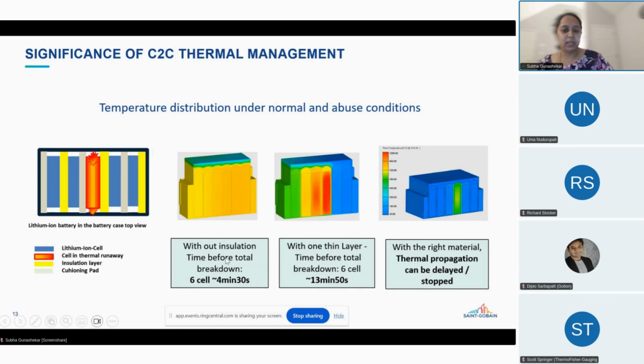So here, through modeling, what we're trying to show is that without any thermal insulation, once the cell goes into thermal runaway, it spreads to the rest of the cells very, very quickly. In this case, it was about 4 minutes. Adding one layer of material can help slow that down. But again, if the right choice of material is not used, it could continue the propagation, but at least your time has increased. From 4 minutes, it has gone to 13 minutes. Whereas if you have the right kind of material, your thermal propagation can be delayed or stopped.